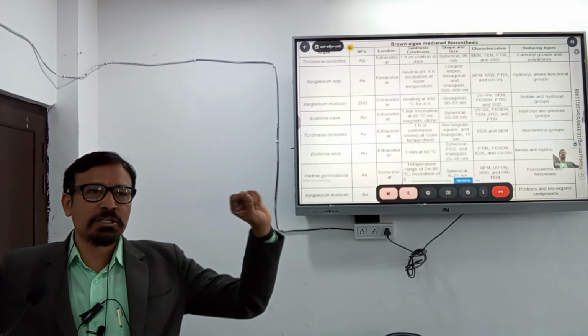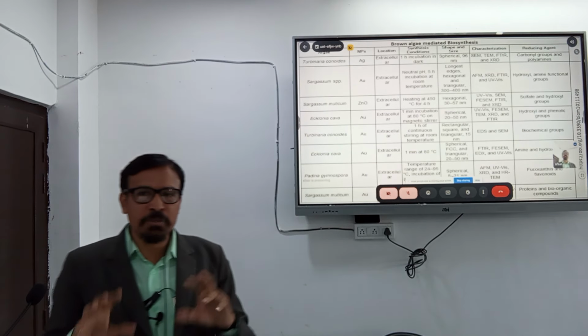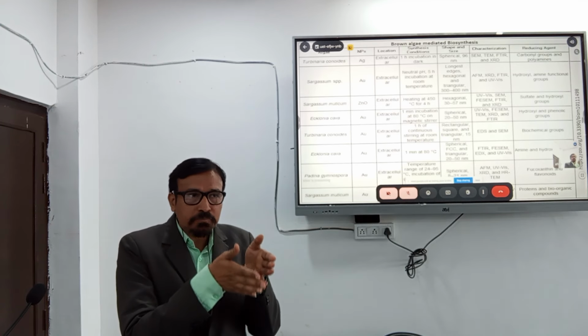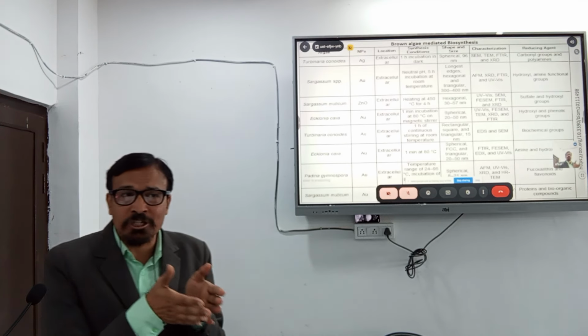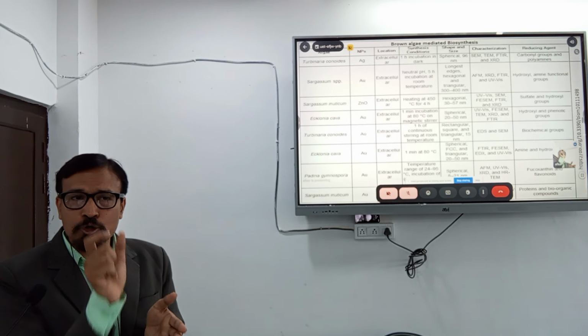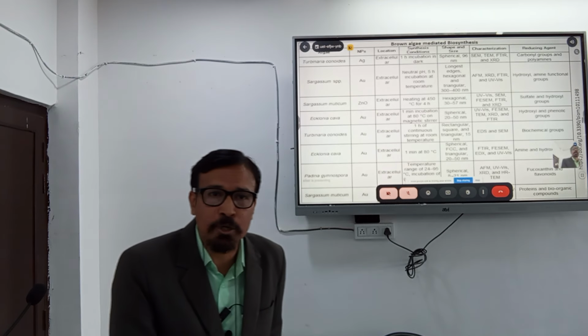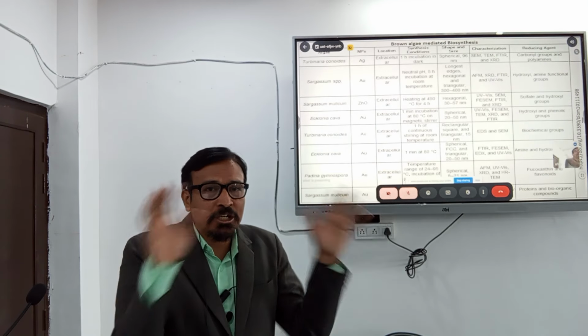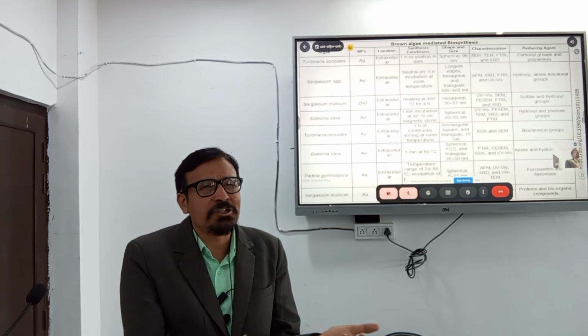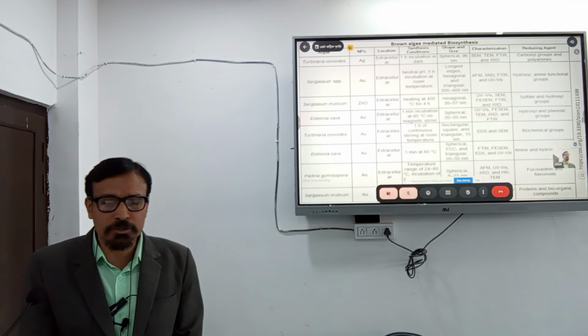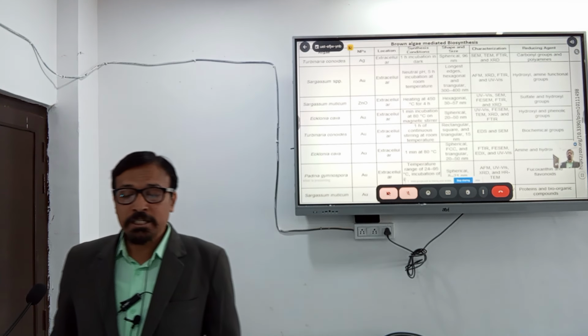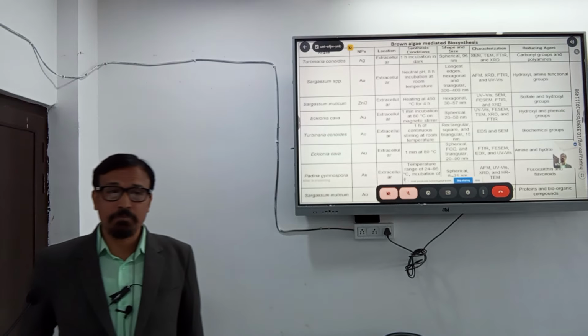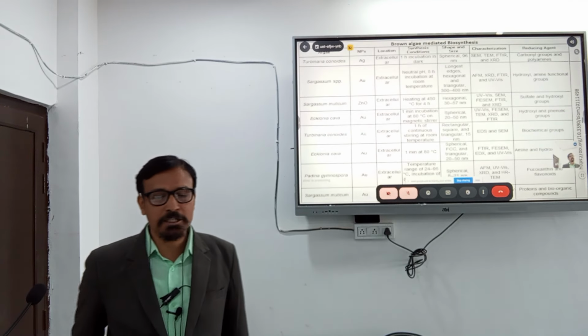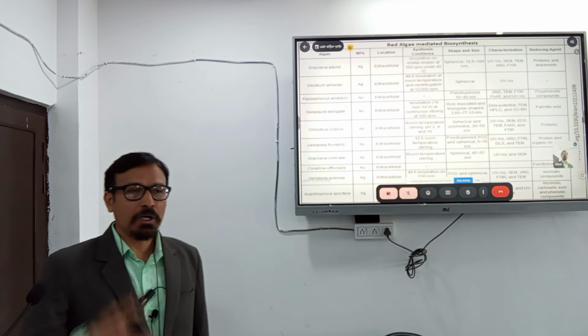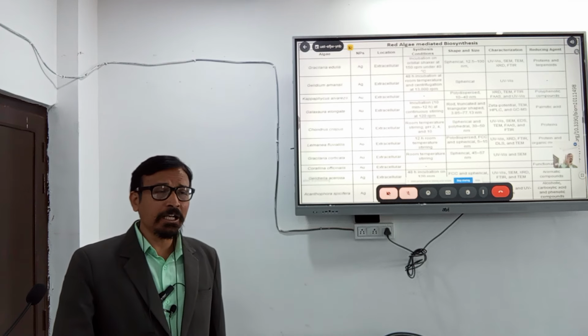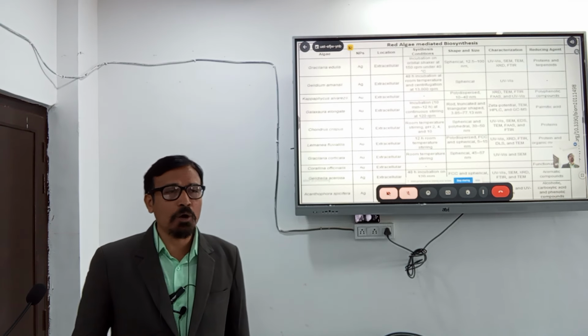So if there is more minus or more plus, that means there is less agglomeration of those nanoparticles. Otherwise it is close to zero, that means there is more agglomeration, there are larger molecules of the nanoparticles, which is of no use. So these are the proteins and bioorganic compounds as the reducing agents present in the Sargassum muticum. So till now I described the brown algae.